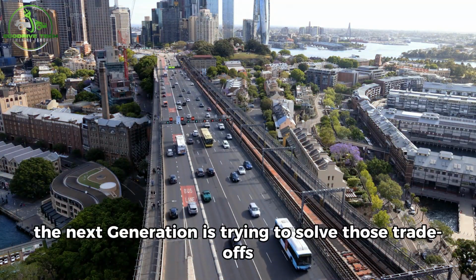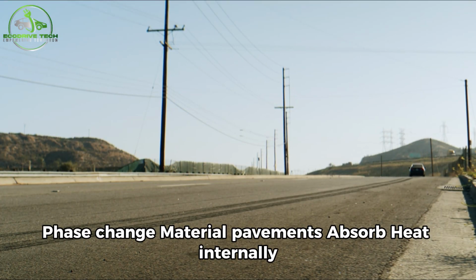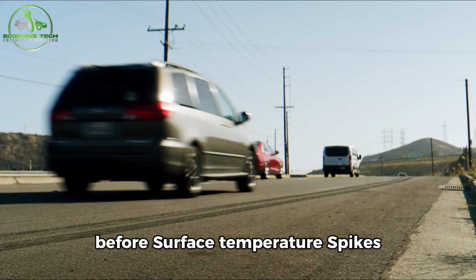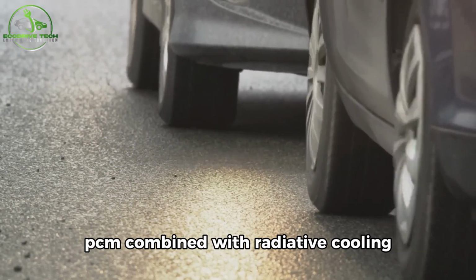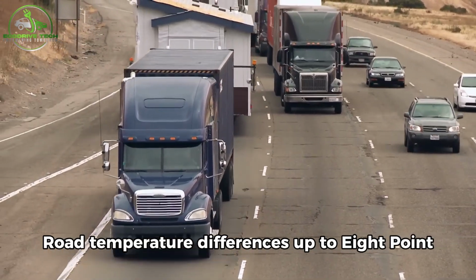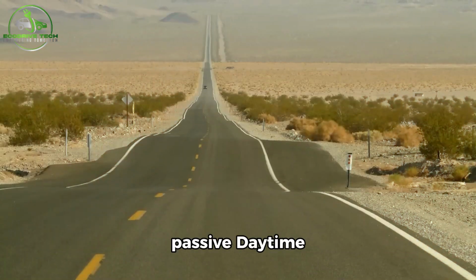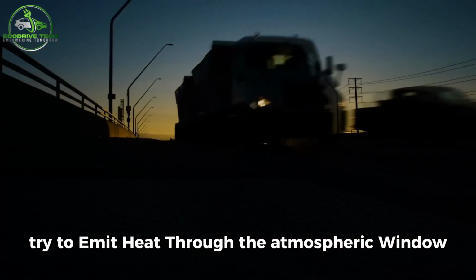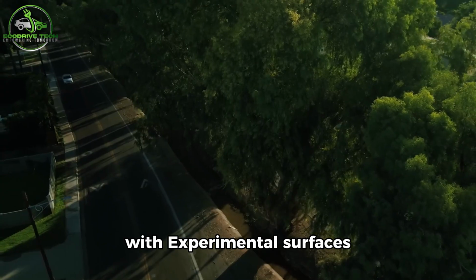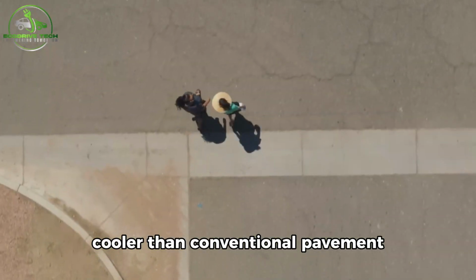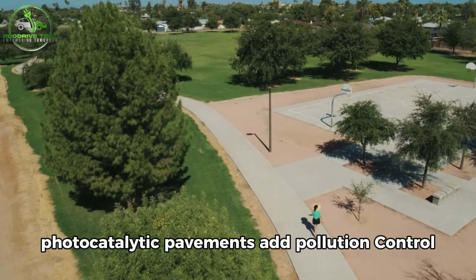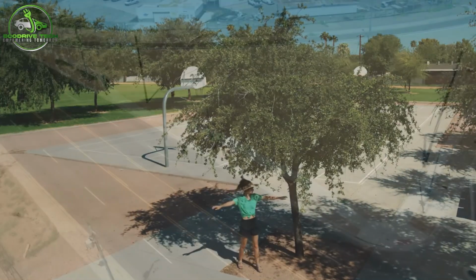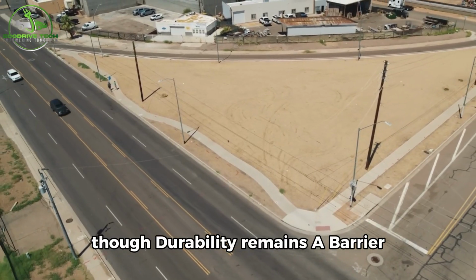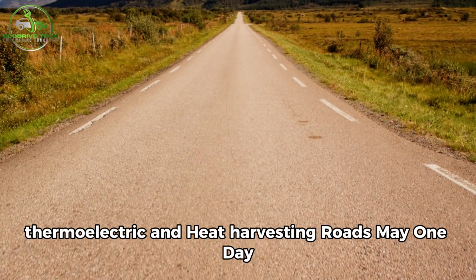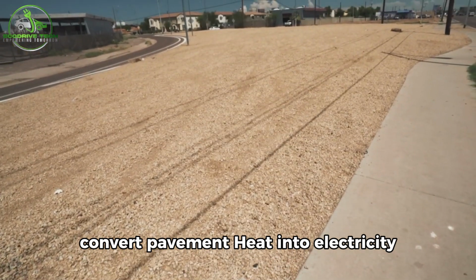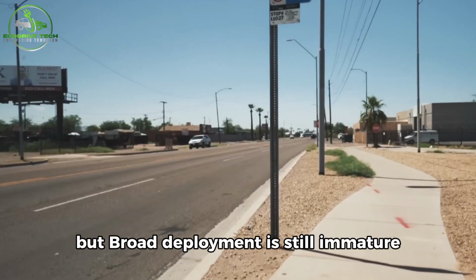The next generation is trying to solve those trade-offs. Phase change material pavements absorb heat internally before surface temperature spikes. PCM, combined with radiative cooling, has reported road temperature differences up to 8.7 degrees Celsius. Passive daytime radiative cooling pavements try to emit heat through the atmospheric window, with experimental surfaces up to 11 degrees Celsius cooler than conventional pavement. Photocatalytic pavements add pollution control, with NOx removal reported up to about 55%, though durability remains a barrier. Thermoelectric and heat-harvesting roads may one day convert pavement heat into electricity, but broad deployment is still immature.